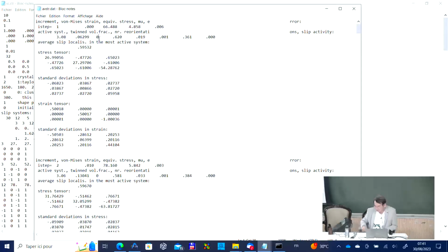It's enjoyable to read with what precision the simulation could reproduce not only the texture itself, not only the strain hardening curve, but also the general volume fractions and individual variants in 100 grains which were studied individually in the magnesium compression testing.